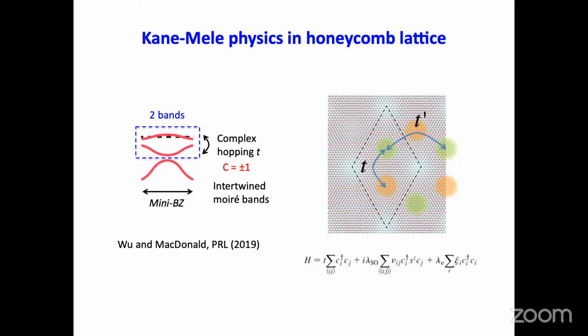Yeah, you have to think that the kinetic energy defined by the Moiré period, which is basically h bar squared divided by the mass of the electron divided by the Moiré period squared, that energy scale has to be comparable to or smaller than the interlayer hopping term between the two layers, right? Because it's the periodic modulation of the interlayer hopping that produces the Moiré potential. So in some sense, the Moiré potential has to be strong compared to the kinetic energy defined by the Moiré period. Okay, is that sort of clear?